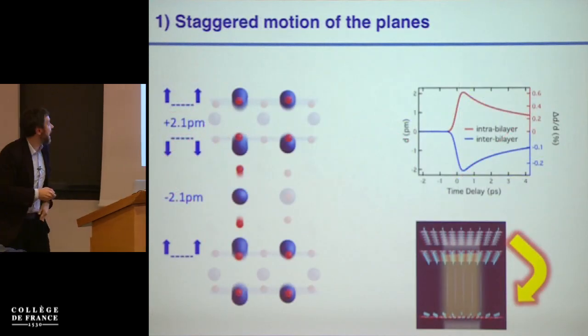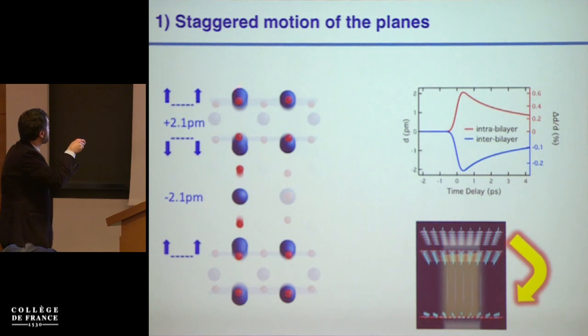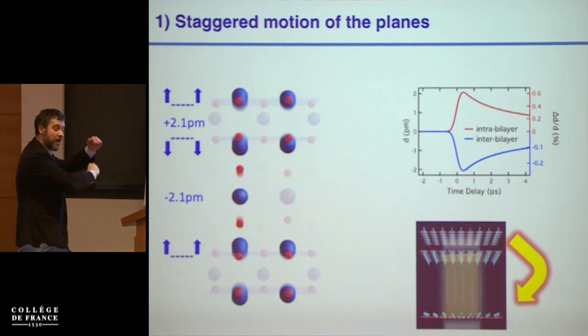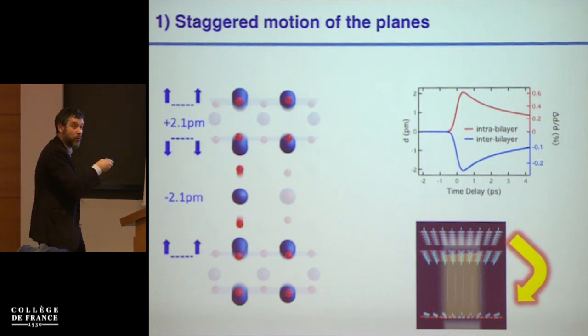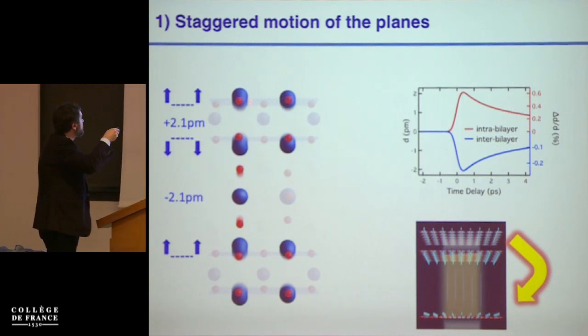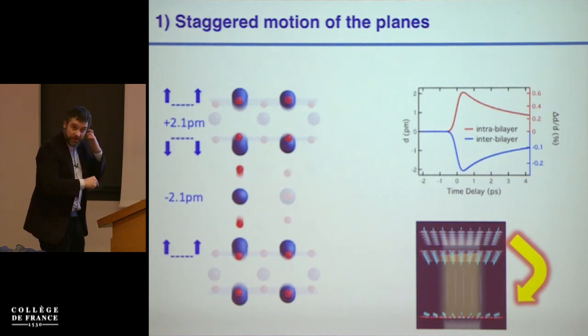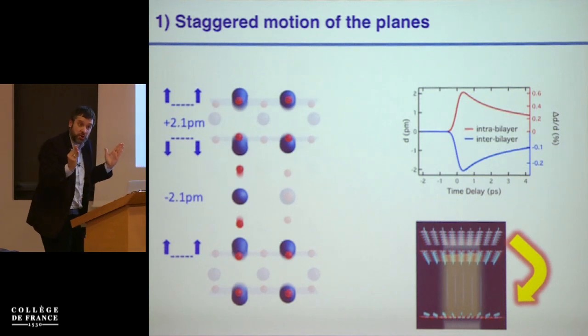The second thing that happens is that one observes the fact that some atoms walk apart within the unit cell, which might explain why the tunneling between these planes was getting weaker. And these atoms become closer between the bilayers, which might explain why the Josephson coupling was getting stronger between the planes. So this in principle is also a good thing.